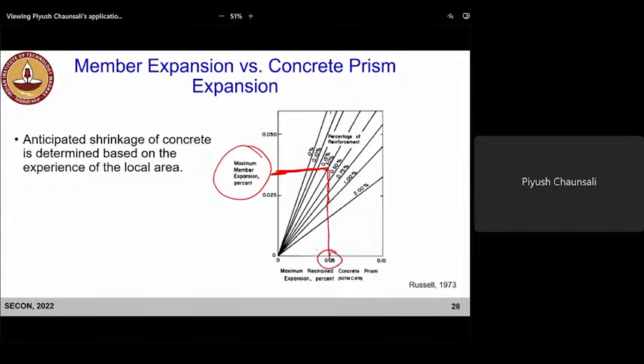this is on the x-axis, you have restrained concrete prism expansion. So as per ASTM C878, we can cast these concrete prisms in restrained condition, and we would like the expansion to be this much. That will mean that if we now use that concrete in the slab which has 0.3% reinforcement, it will give you this much compensation. Basically this much expansion will happen, and that will make this concrete shrinkage compensating.